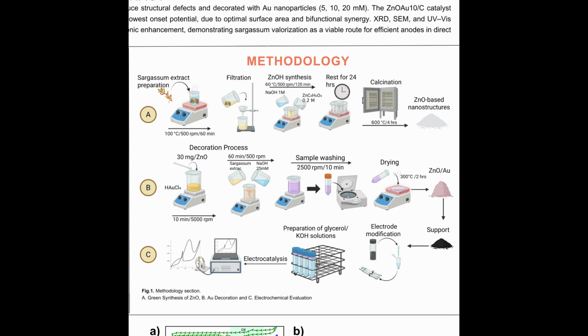Stage A: green synthesis of zinc oxide nanostructures. An aqueous extract of Sargassum natans 1 served as both reducing and stabilizing agent. Its rich composition in polyphenols and other reducing molecules facilitated the nucleation of zinc oxide nanostructures, while creating oxygen vacancies and other lattice defects known to increase the density of active sites and improve electron transfer. The zinc oxide powders were then calcined to enhance crystallinity while retaining defects.